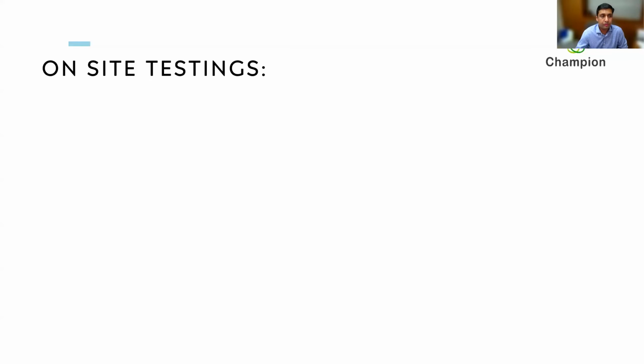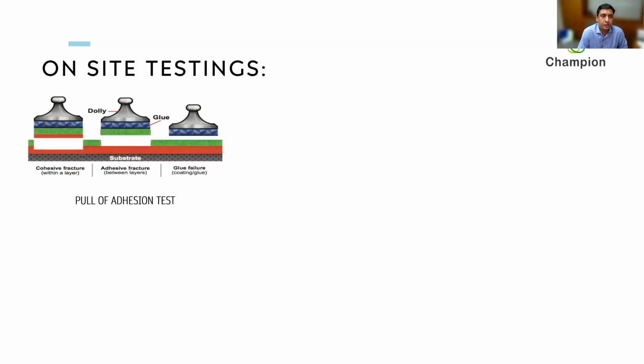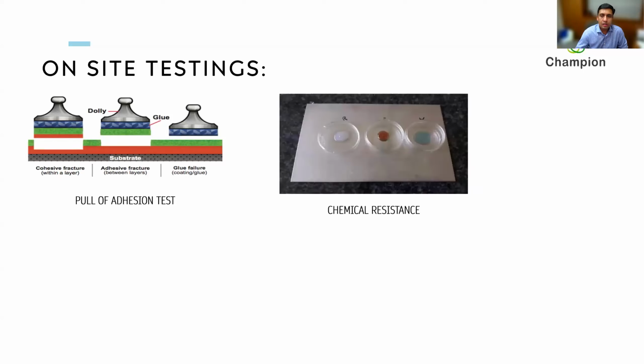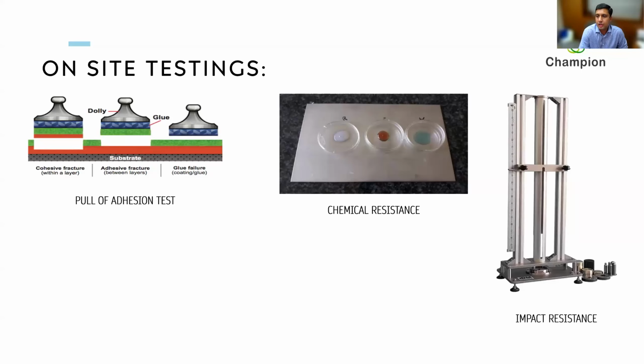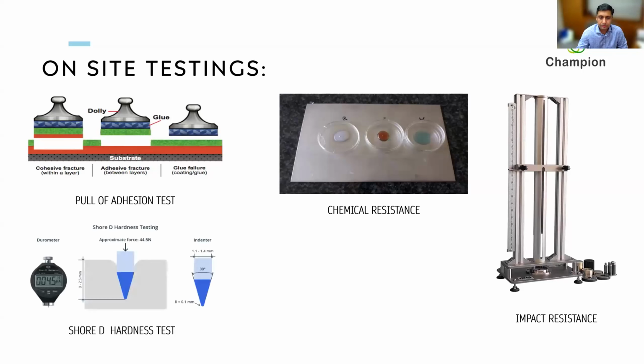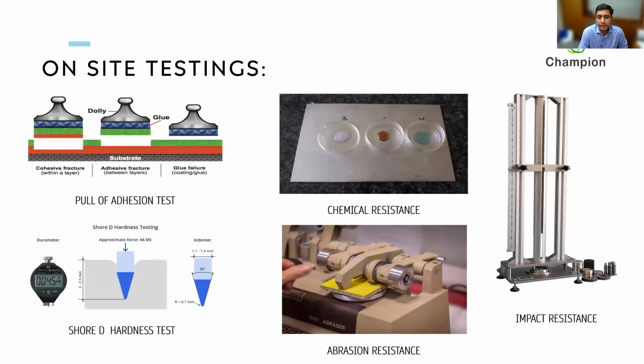Now, what I'm going to talk about briefly is the type of testing that people would like to do on a flooring. The first and most common test is a pull-off adhesion test to ensure that the flooring is well bonded to the substrate. The second type of test is a chemical resistance test. And in this case, we are just showing a drop test with the chemical staying in a small surface area. But one can do various types of chemical resistance tests and even cyclic corrosion tests, which are very much possible. The third type of test is an impact resistance test, which can be for various types of mechanical properties. The fourth test is for the hardness, which is typically for surety. And the fifth type of test is for abrasion.